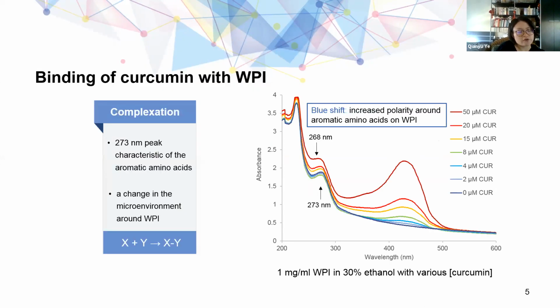UV-vis absorption spectroscopy was applied to study possible interactions between denatured WPI and curcumin. A peak at 273 nanometers is characteristic of the aromatic amino acids in proteins. It was blue shifted to 268 nanometers with the addition of curcumin. This indicates a change in the microenvironment around the WPI due to the interactions between curcumin and the denatured WPI.